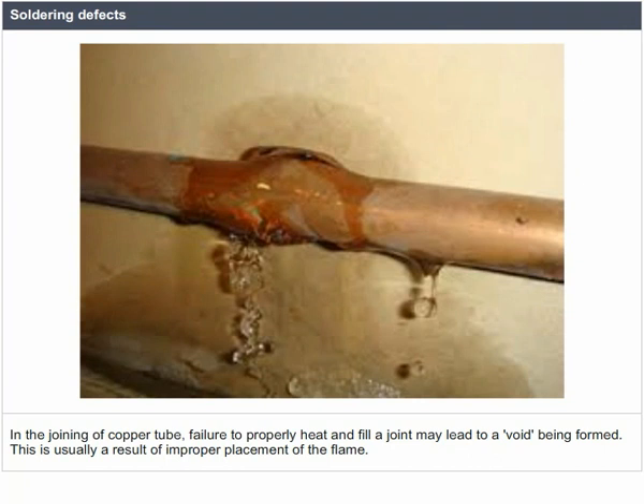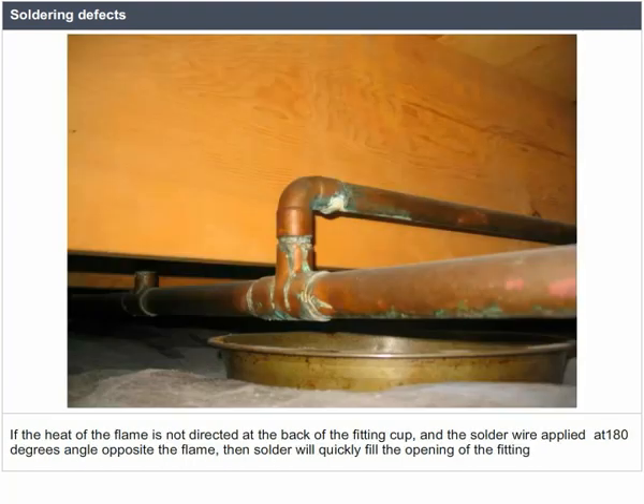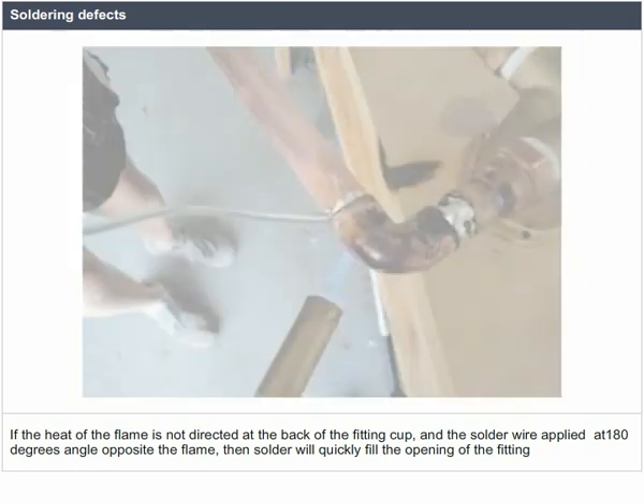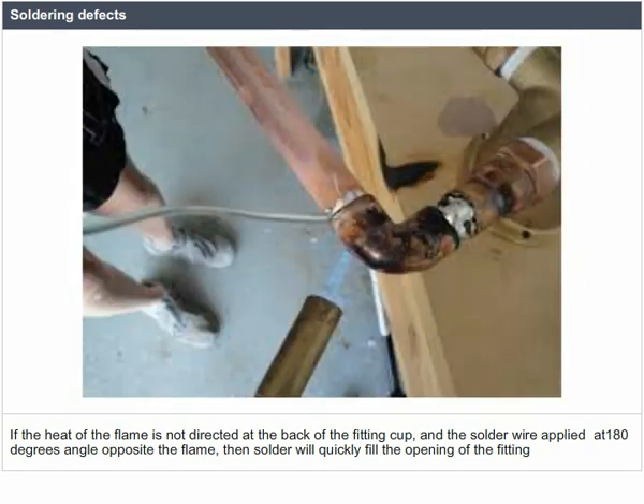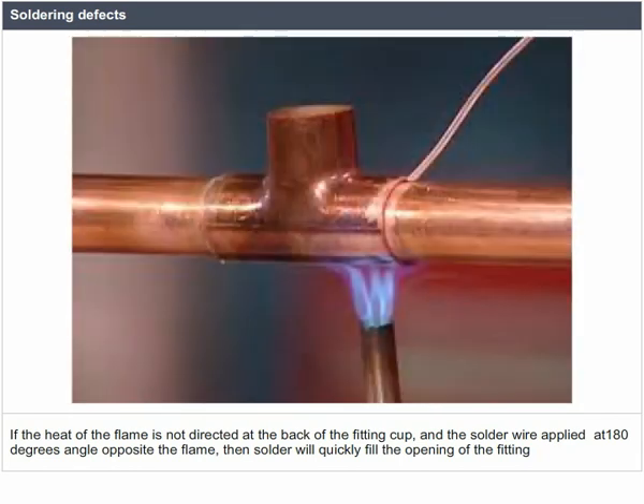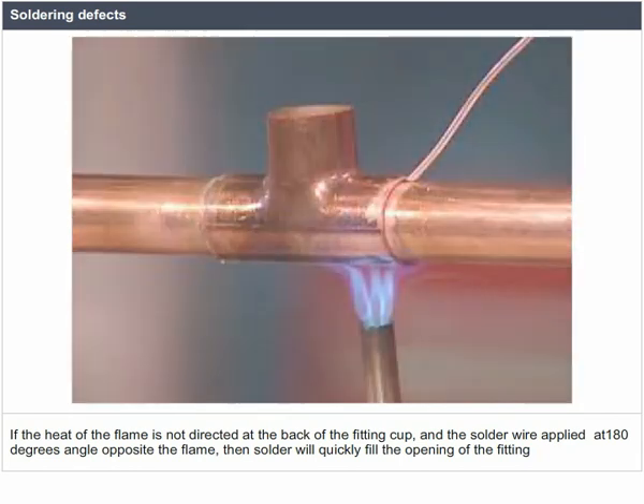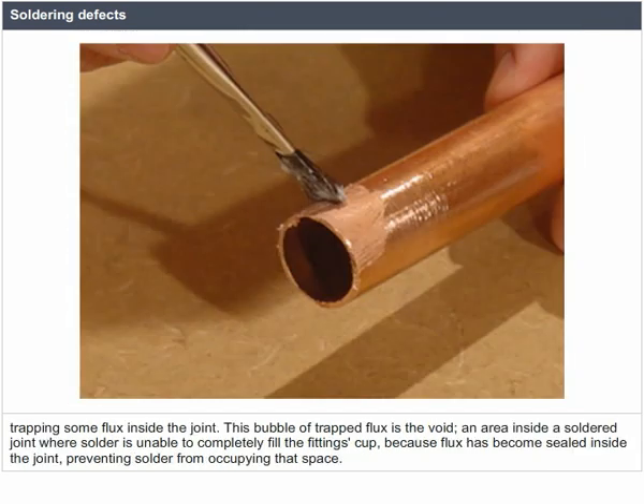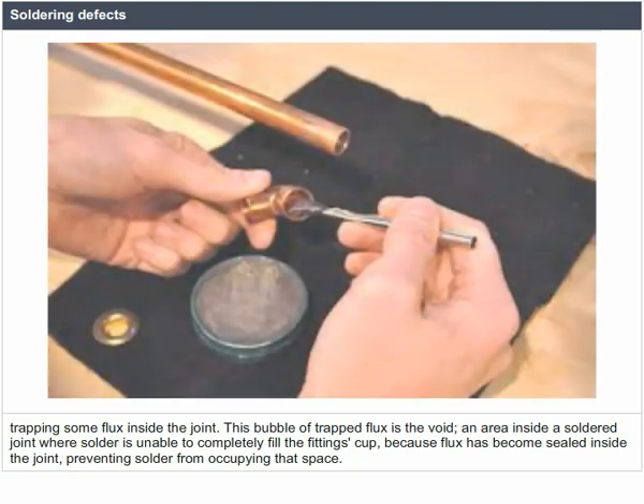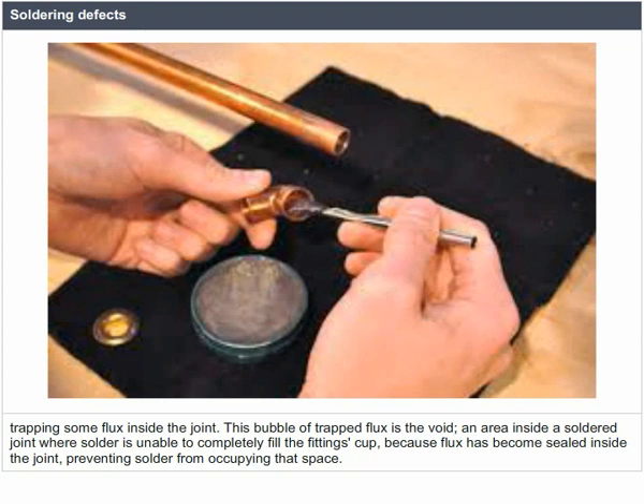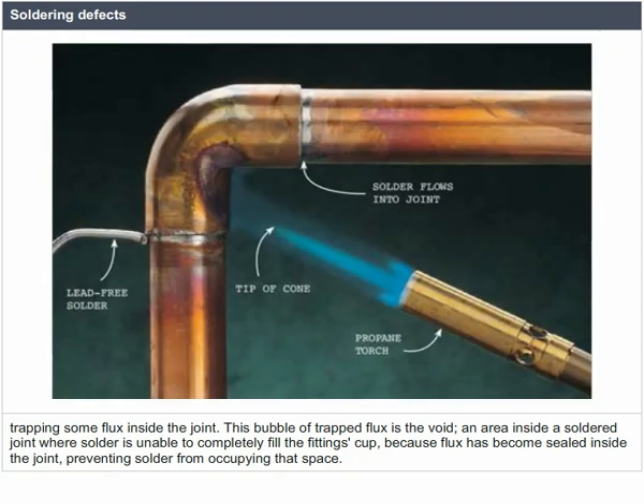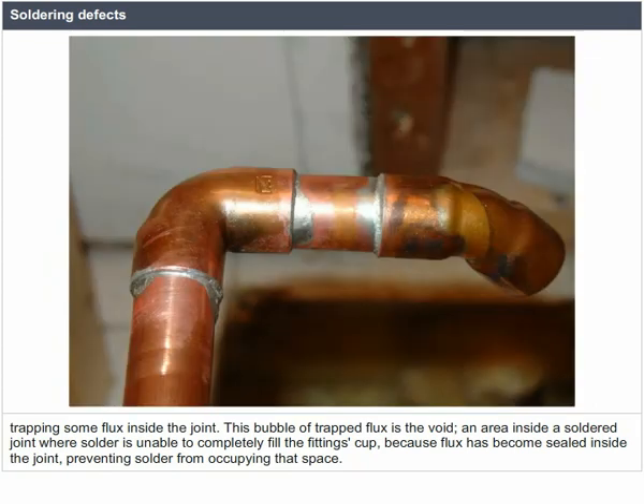If the heat of the flame is not directed at the back of the fitting cup and the solder wire applied at a 180 degree angle opposite the flame, then solder will quickly fill the opening of the fitting, trapping some flux inside the joint. This bubble of trapped flux is a void, an area inside a soldered joint where solder is unable to completely fill the fitting's cup because flux has become sealed inside the joint, preventing solder from occupying that space.